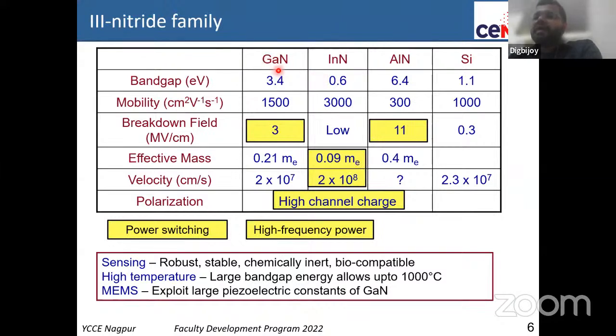I just want to highlight the fact that gallium nitride, with respect to silicon, has much more advantages in terms of some fundamental material properties, say breakdown field. So breakdown field tells you at what electric field strength the material can break down electrically. You can see that the breakdown field of gallium nitride is roughly 10 times that of silicon, which means for a given material dimension, gallium nitride can block 10 times higher voltage than silicon, which naturally means that for having high voltage, high power kind of devices, gallium nitride can perform better than silicon in principle.